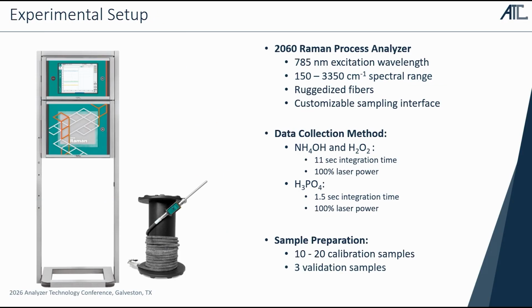So for the experimental setup, to move this industry standard of using NIR towards Raman spectroscopy, we used a process analyzer, 785 nm excitation wavelength. We needed a broader range from 150 to 3350 wavenumbers. And of course, for the implementation in a process environment, we need everything very ruggedized and customized, because each environment looks different and needs the specific interface to get good spectral data. To show you how fast everything is, the integration time for each sample is about 11 seconds. That means every 11 seconds you would get a new data point of what is actually happening in this bath.